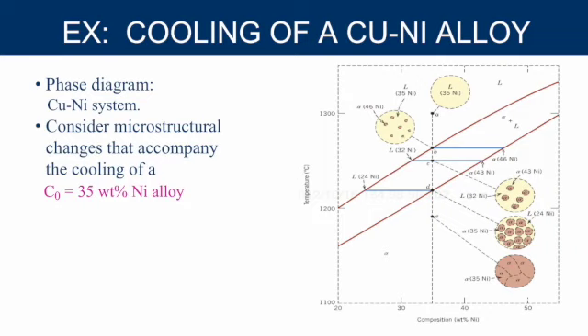Okay, so what's happening in these phases? So we have this phase diagram. This is our copper-nickel phase diagram again. We're just looking at a small region. And you'll see this a lot with a lot of our phase diagrams. Carbon and iron is a good example. To make steel, there's a very small range of carbon that can be added to iron to create steel. So there's really no reason to show the entire phase diagram from 0 to 100. They only show a very small region because that's the only usable region. The other parts make unstable materials.